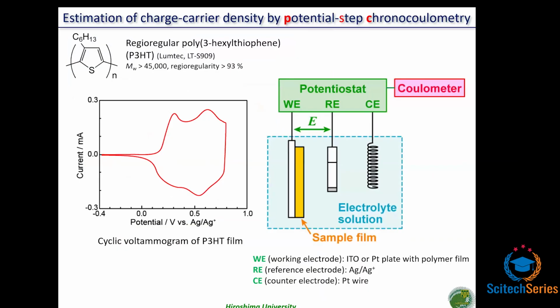To estimate the charge carrier density of π-conjugated polymers, we utilize the potential step chronocoulometry, PSC, which is a kind of electrochemical measurement. Here I explain this method using poly(3-hexylthiophene), P3HT, as a typical example of π-conjugated polymers. For the PSC measurement, we needed to understand the redox properties of the polymer. So before the PSC measurement, cyclic voltammetry is carried out using a 3-electrode system. In this system, an ITO plate coated with the polymer is used as a working electrode.